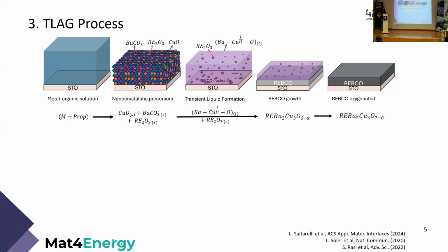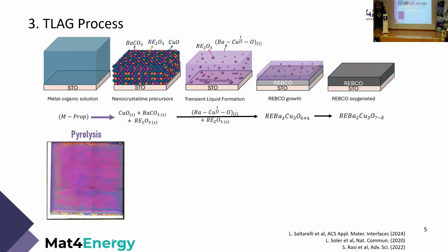After the deposition, we then produce the REBCO film through the novel TLAG process, which has been developed in the group in the past 15 years. And it mainly consists of 3 steps. First, there is a pyrolytic process in which we remove the organic part, and we end up with a nanocrystalline precursor of copper oxide, barium carbonate, and rare earth oxide.